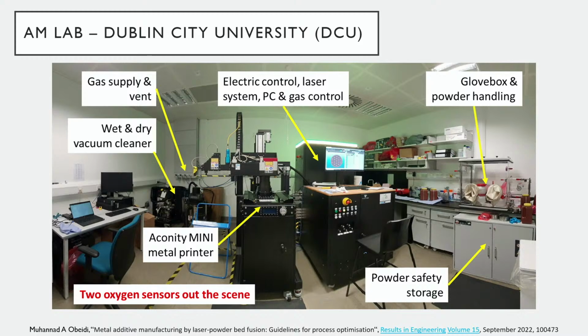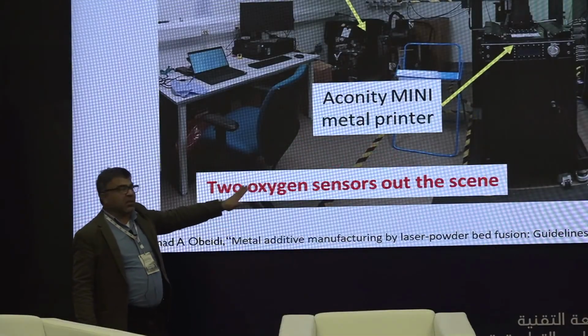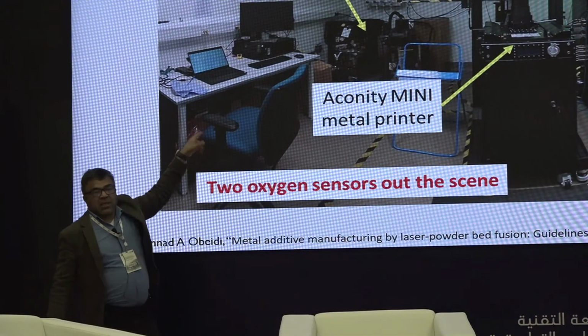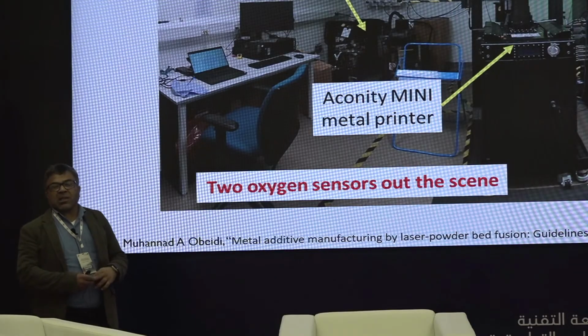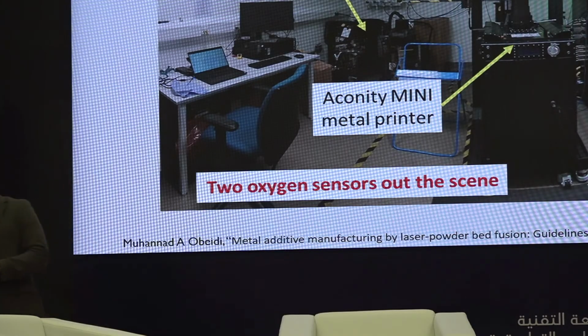Some metal powders, for example, magnesium, can catch fire if you hold it by your hand from your body temperature. So that's why when we handle the powder, we store them here in a fire retardant storage, 90 minutes fire retardant, and then we transfer them from the export containers, big containers, to smaller containers, and then again, inert gas conditions, glove box. And then we load it to the printer. Just in case of any leakage, and we have argon to avoid suffocation, we have oxygen sensors installed around the machine just for the safety of the operator.